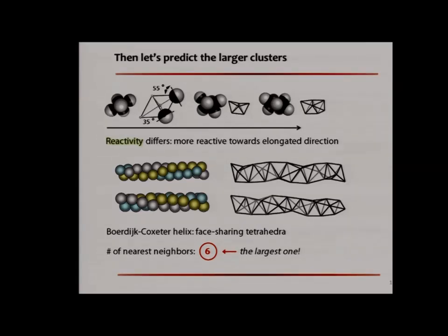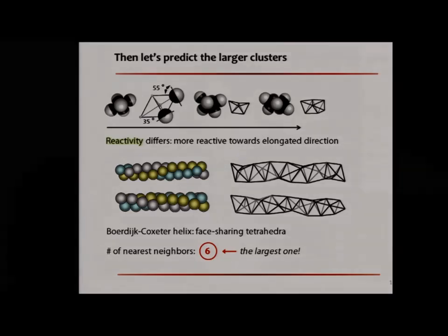Another interesting thing here is that for the particles within the helical chain, each always has 6 nearest neighbors, which is the maximized coordination number for a half-half geometry Janus particle. So that means the helical chain is not only the structure that is kinetically favored, it's also the structure with the lowest enthalpy. So in my experiments, I pursued the prediction by making my Janus particles more approachable to each other so their self-assemblies can grow larger. There are examples when predictions don't come out in reality, but this time it worked.